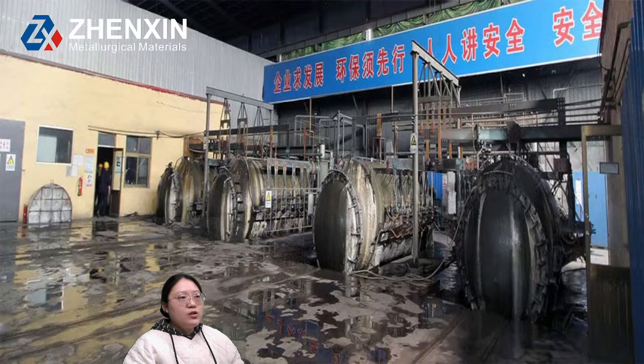The typical nodulizer has magnesium content of about 5 to 9%, silicon content about 44 to 48%, and calcium content around 1%. Rare earth is always optional, and the iron element is always the balance.